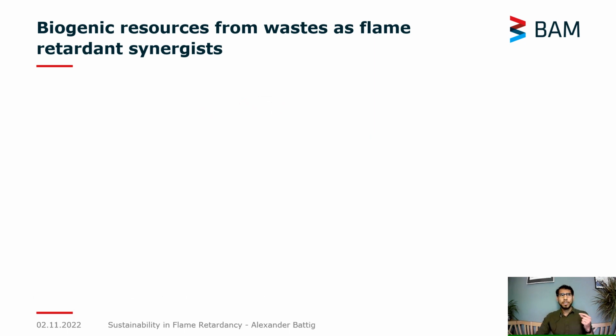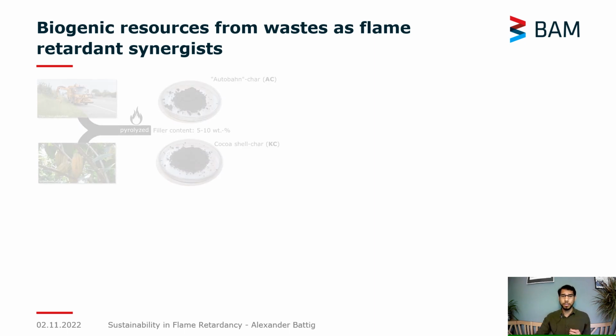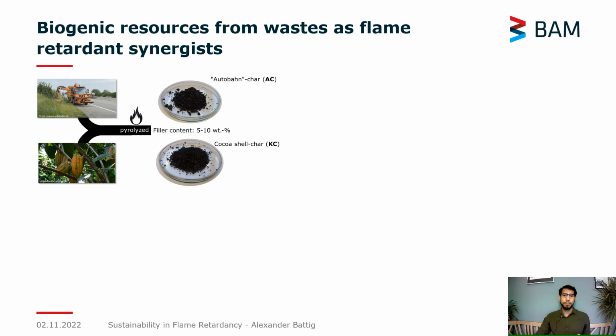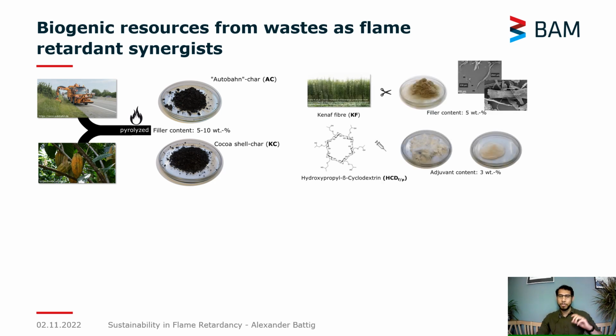Moving on, a different approach that we used to investigate other types of biogenic fillers was using what's known as biochar. We used two different types of biochar. One from cocoa shell and the other one from what we called autobahn char. Essentially, this is a wood char that is produced from the shavings from the side of the road. Whenever you see these construction cars driving by the autobahn, shaving off the grass and the weeds on the side, this material was captured and then pyrolyzed to create a strong wood char we called autobahn char. This material was combined with kenaf fibers and also with cyclodextrines in biosourced epoxy resins.